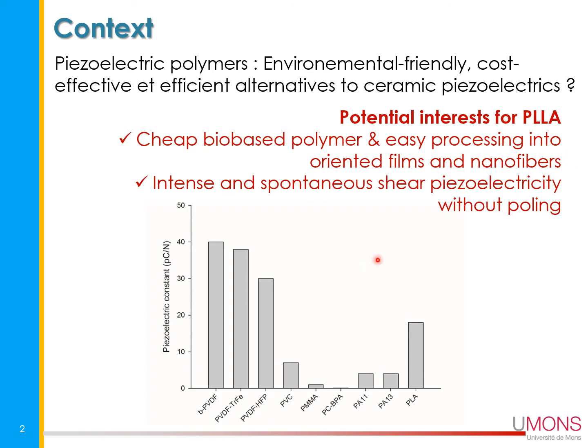And also, which is extremely important, it presents intense and spontaneous piezoelectricity without any poling of the polymer. So indeed, what you see here is that PLA presents a very nice, interesting and promising piezoelectric constant compared to the other polymers.